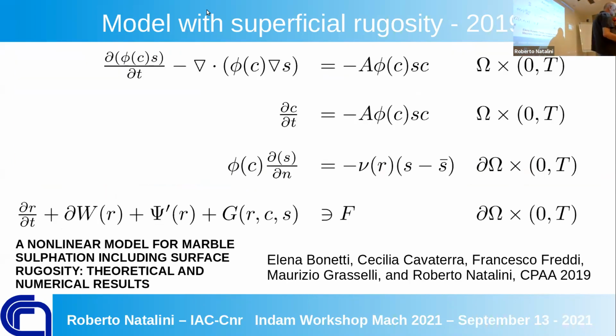So we introduced a model where we covered the previous model, but with the rugosity term, which is just acting on the surface. This rugosity is a quite complicated idea because it's very difficult to measure rugosity. You ask a physicist, there are different definitions. There is a roughness, rugosity, and also the tools. It depends on the tools you are using to measure this kind of quantity. But anyway, this idea that your surface is going to be more complicated, and so in some sense, you expect that the absorption of the pollutants is different, but there is a limit when maybe it is too intricate and so too complicated, so it is a sort of filter.